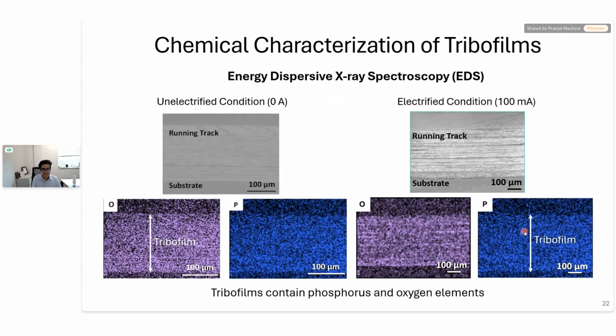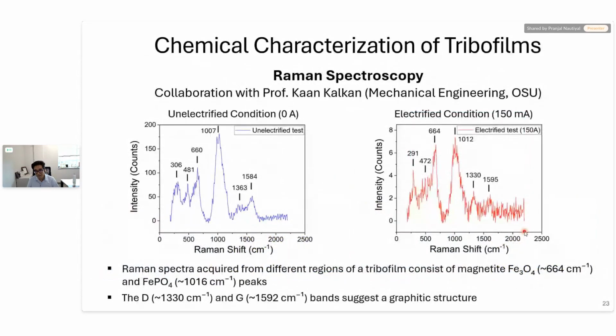We also looked at the composition of these tribofilms, and they are composed of phosphorus and oxygen, which is consistent with previous studies on phosphonium phosphate ionic liquid films generated under unelectrified conditions. The application of electric field did not change these elemental compositions significantly. We also looked at their composition by Raman spectroscopy. This work was done with Professor Kaan Kalkan's group at Oklahoma State. And we saw that the tribofilms were primarily composed of iron oxide and iron phosphate, along with some carbon peaks. So the composition of the tribofilms was more or less similar for both unelectrified and electrified conditions. The application of electric field did not change the chemistry of these tribofilms significantly.